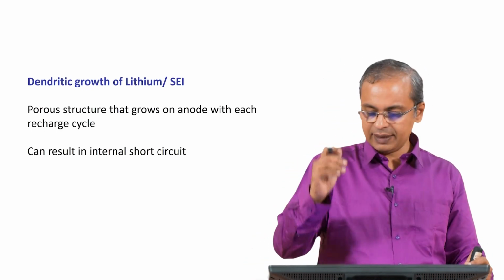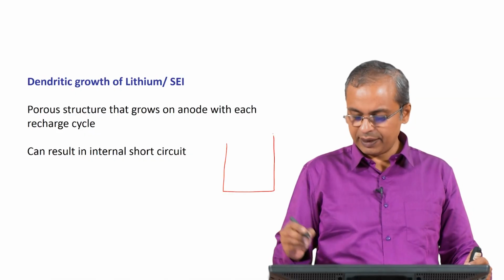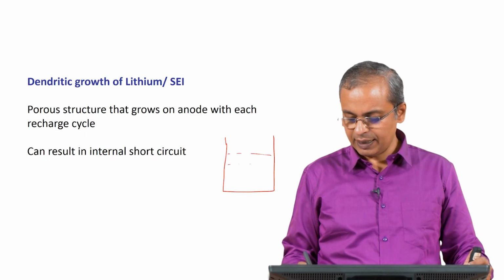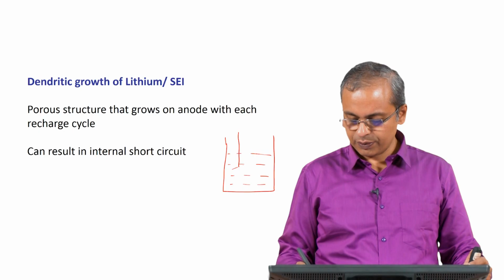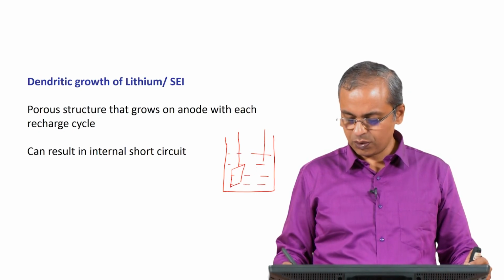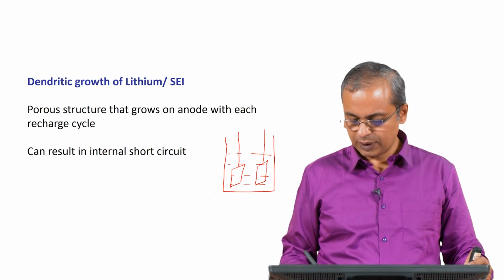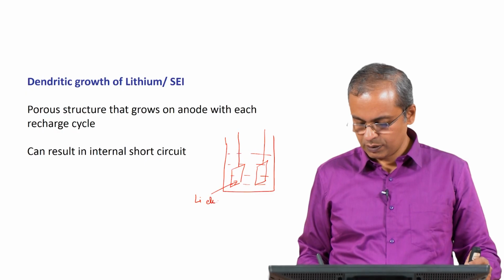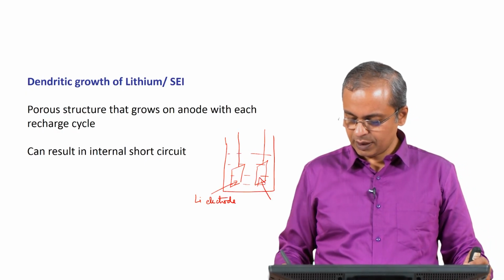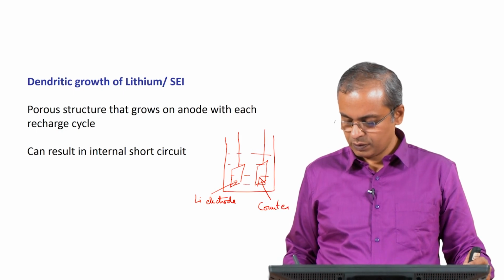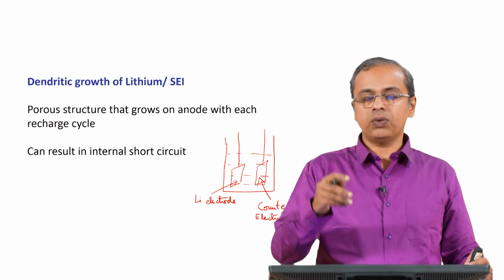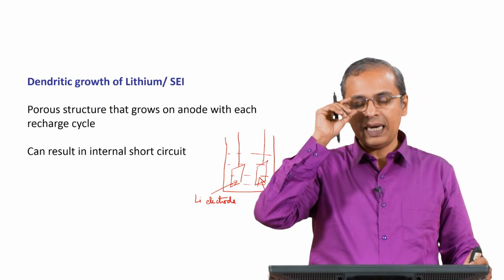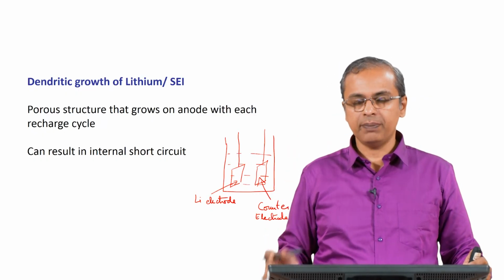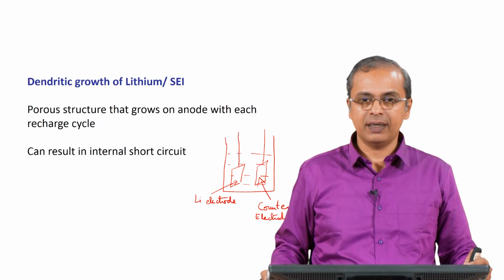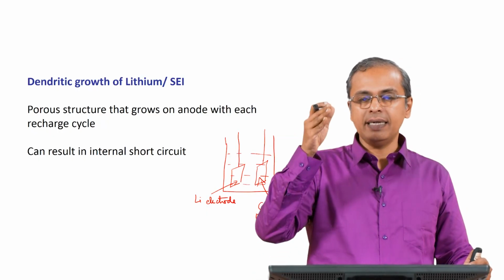So, what happens when we create a cell? Let us assume I have made the cell in an inert atmosphere, and then we have the electrolyte here. Let us say we just put one electrode of lithium here, another electrode of something else, some counter electrode here. So, I will just call this the lithium electrode, and this is the counter electrode. Right. So, as soon as the lithium electrode sees the electrolyte, the surface of the electrode reacts with the electrolyte. It immediately reacts with the electrolyte and forms a passivating layer. Reacts meaning it gets oxidized by the electrolyte and it forms a passivating layer.